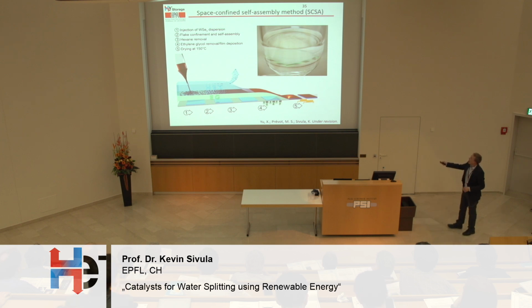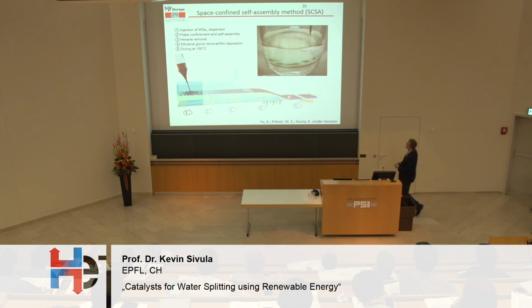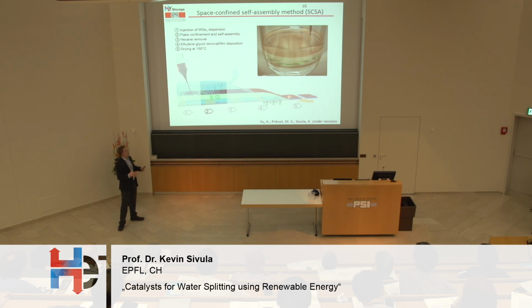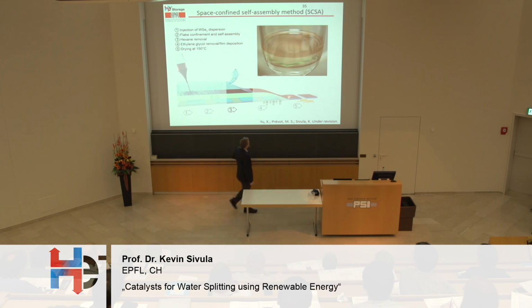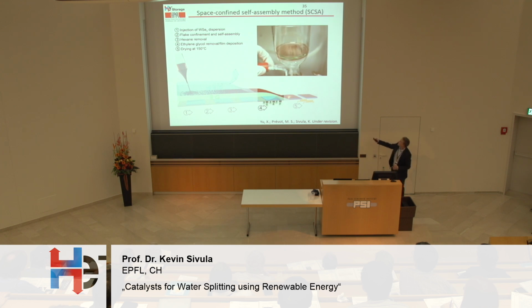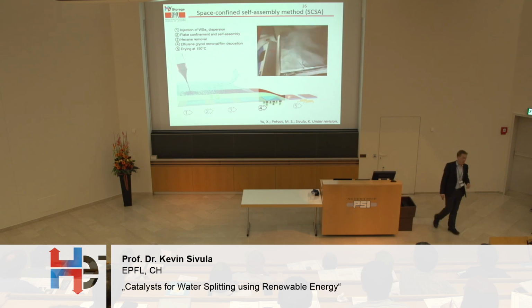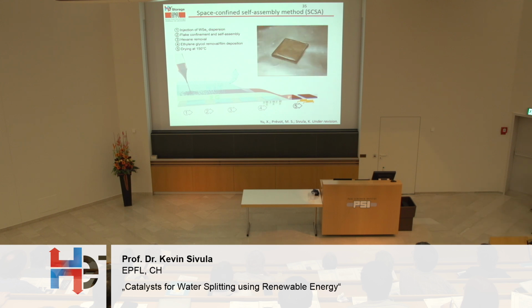I show you it here just in a batch, and right here is the interface between the ethylene glycol and the hexane. And you can see we inject the dispersion of the transition metal dichalcogenide. Remember, we got this just by shaking up a solution of material that we bought from Sigma Aldrich. Then we remove this top phase just with a syringe. And finally, we remove the bottom phase out of this frit. It looks quite nice. We have to take the sample over to a hot plate just to evaporate that solvent, but after a few minutes, we have a film that looks fantastic.